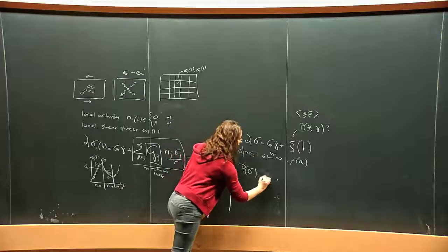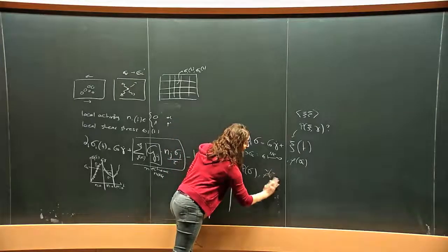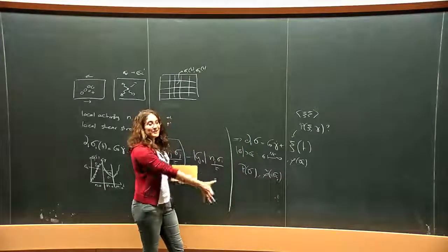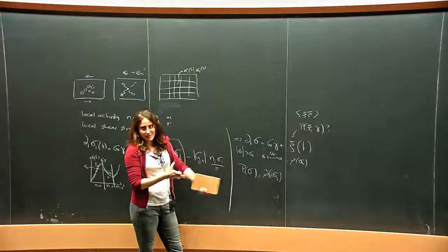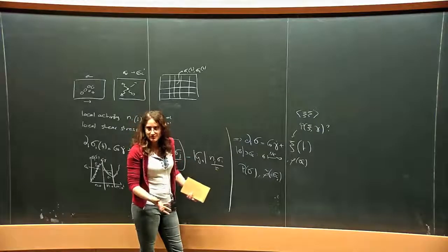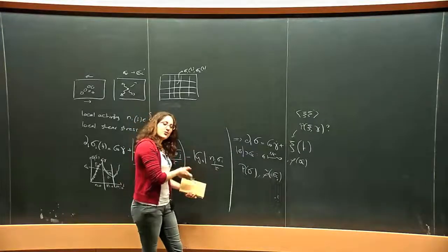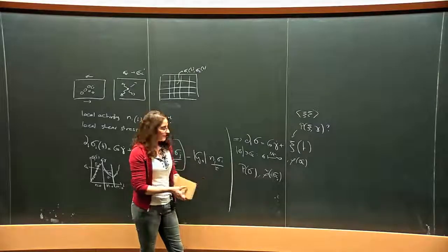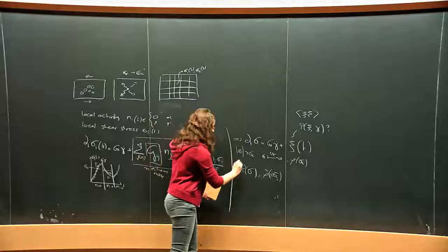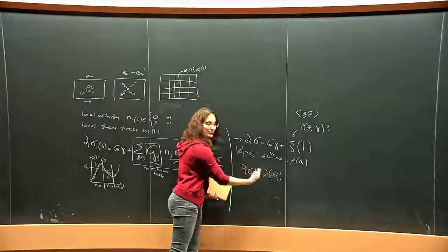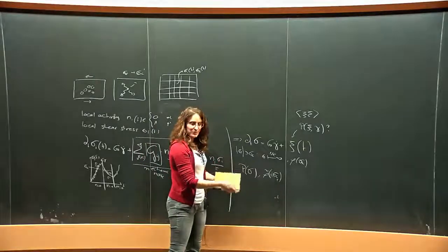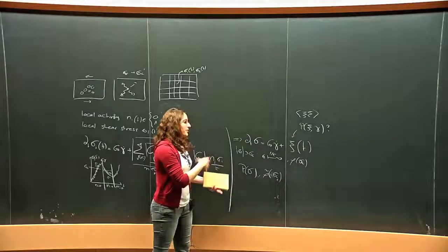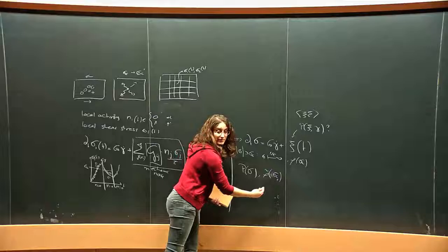But you can also study the fluctuation of the barriers themselves. And in the steady state already, you will see that depending on how fast you shear, you will have a different distribution of the barriers that you have in your system. You will destroy more easily small and large barriers depending on the driving that you have. But you need for that to have from the beginning a distribution of barriers in your model, which was not necessarily the case in the first version of Hébraud-Lequeux, but in SGR, of course, that was one of the key ingredients.